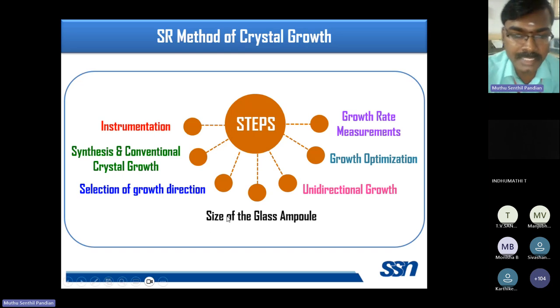And the different sizes of the glass ampoule mainly depend upon the solubility of your material. If it is very highly soluble, you can choose a very high ID and OD, which means the inner diameter and outer diameter of the glass ampoule. If it is a very low soluble material, you can choose the very minimum ID and OD for the SR method of crystal growth. And for unidirectional growth optimization, we have to maintain two different temperatures, one at the top portion and another at the bottom portion. Depending upon the temperature you have applied at the top and bottom portion, and depending upon the glass ampoule size and the direction, the crystal growth rate will change in the SR method.